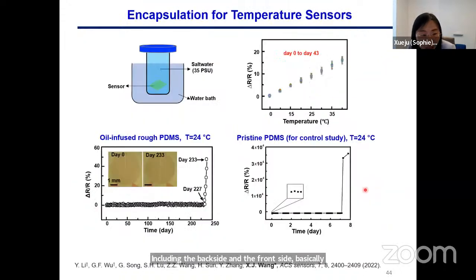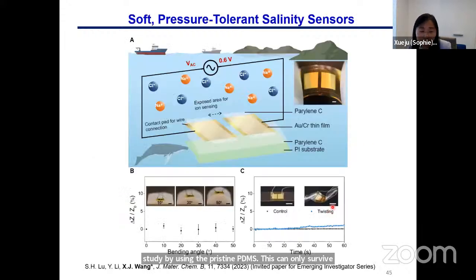Okay, so we further tested the encapsulation capability of the temperature sensor by putting the sensor in a salinity environment. We can see that the sensor can survive the salinity environment for more than 7 months, which is very interesting and impressive compared to the control study using pristine PDMS, which can only survive for a few days in the salinity environment.